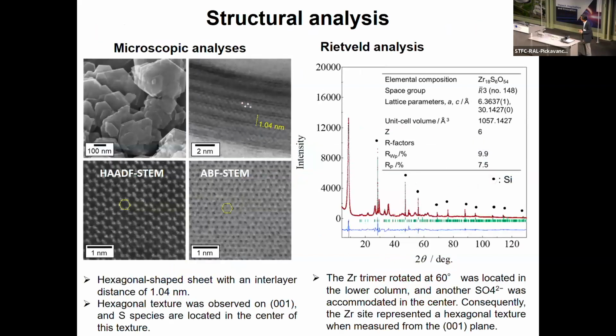We conducted the structural analysis by TEM analysis and other analyses. First, we obtained a very thin plate in a hexagonal shape. This makes it very easy to do HAADF STEM analysis because the material is so thin. The beam comes in and you can collect a clear STEM image. On the left-hand side, which is the HAADF, you can see the hexagonal arrangement of zirconia.